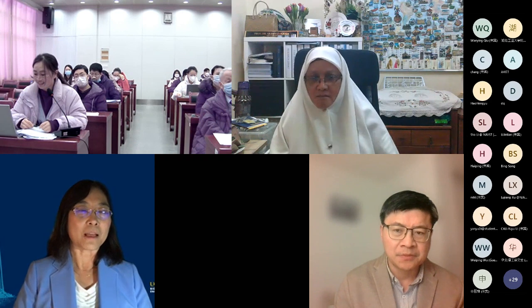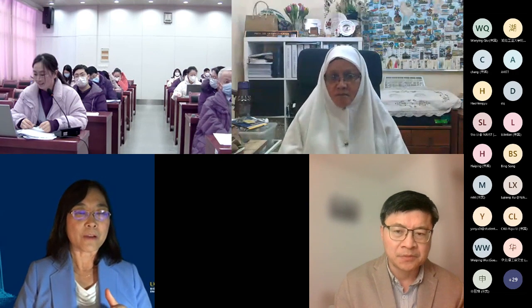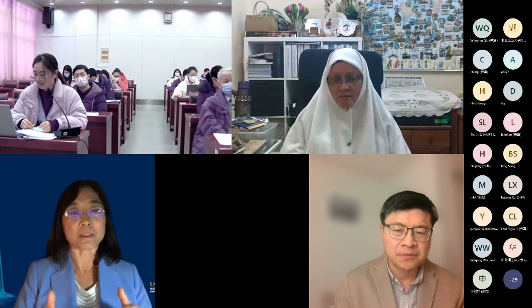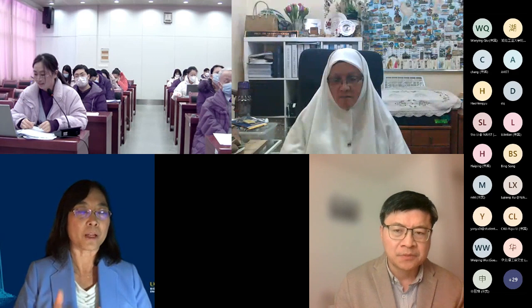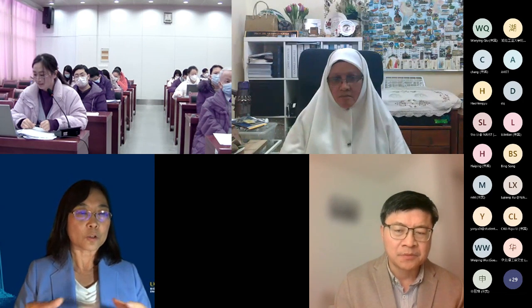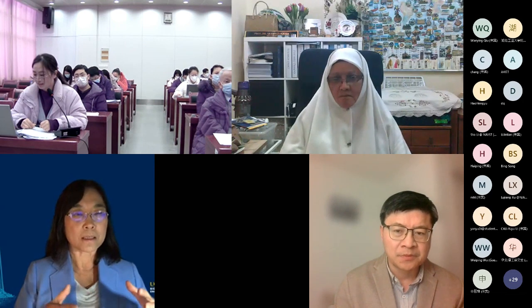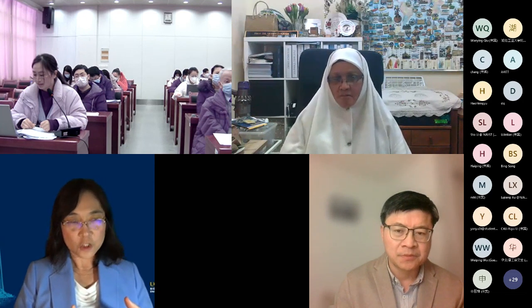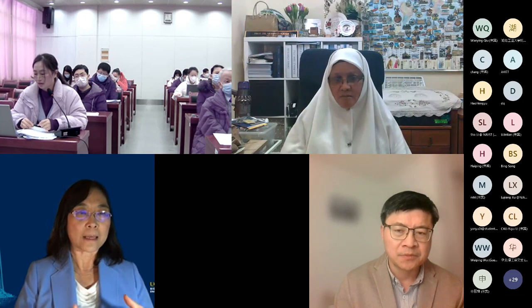So thermophilic digestion is very effective. Thermophilic means 50 to 55, close to 55 degrees Celsius. Thermophilic digestion is very effective in destroying the pathogens. And in our case, we also have 2 phases. The first phase is a low pH, high acid, organic acid.